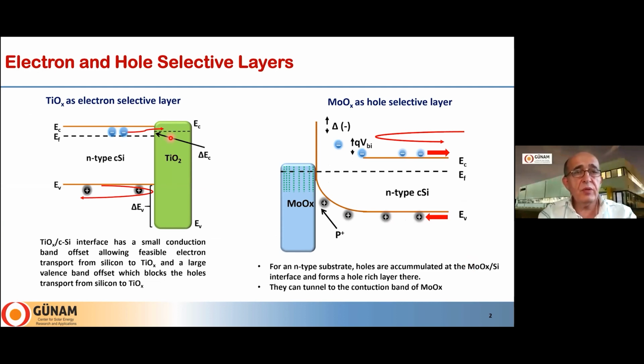Okay, when you use titanium dioxide or titanium oxide, we have a small barrier on the conduction band. This is the band diagram showing the band alignment. But the barrier in the valence band is very large, so the electrons can move through the titanium oxide layer. Okay, so there is a large band offset.